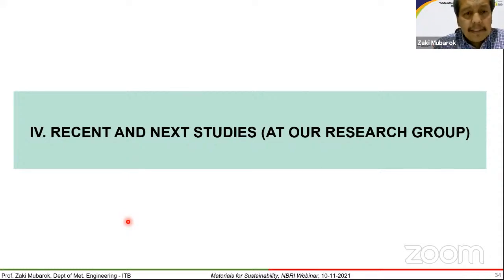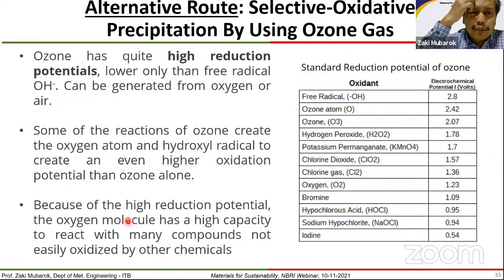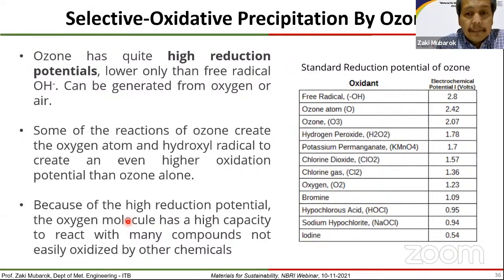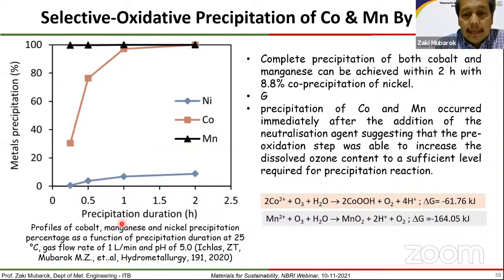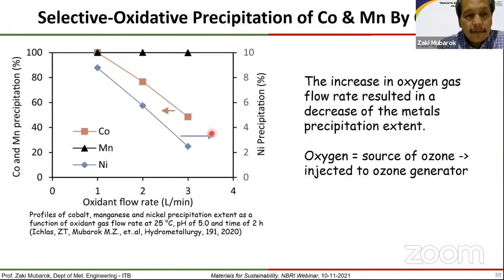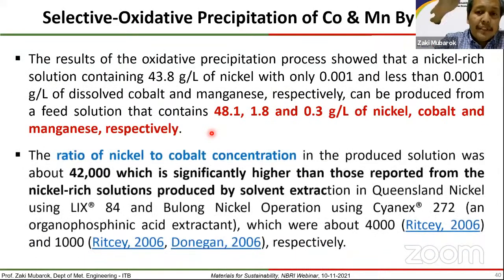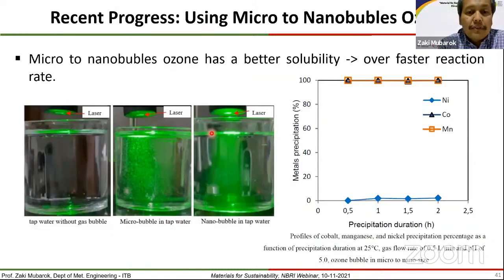And the last part is recent and next studies at our research group. We use an alternative route, so-called selective oxidative precipitation, by using ozone gas. Basically, the ozone oxidizes cobalt and manganese to their trivalent and tetravalent states, and precipitates them in the form of CoOOH and MnO2. You can see here quite good separations, and the ratio of nickel against manganese and cobalt is also quite good, even higher than the solution produced by solvent extraction.